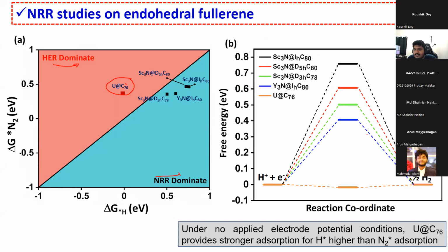This is the hydrogen evolution reaction Gibbs energy plot. And basically, you all know that platinum is the best catalyst for splitting water and for the hydrogen evolution reaction. So basically, this is the thermoneutral value. Thermoneutral value is nothing but the value at 0, and platinum is something around here. The platinum has the value around here. So we found that for uranium C76, it's very close to the thermoneutral value. That's the reason why the uranium C76 has more activity towards HER when compared to NRR.